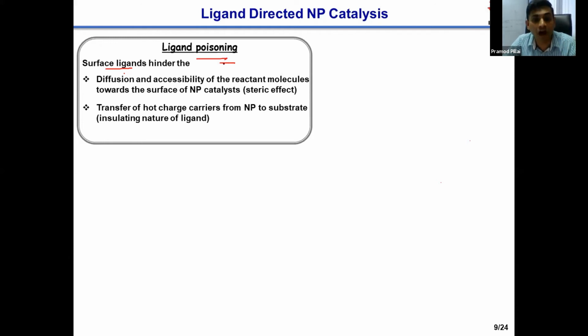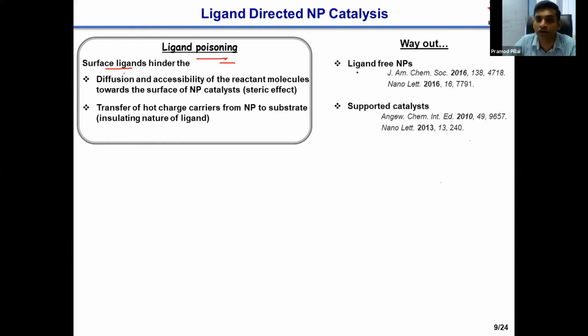So what is the way out here? One of the ways is to work with ligand-free nanoparticles where you don't have any traditional ligand. So these nanoparticles will be stabilized with some small molecules like some hydroxide or some sulfide ions, and they can be used for catalysis. So this is a very good strategy, but the problem is that during the catalysis, the stability of the nanoparticles gets compromised because you don't have a traditional ligand which will stabilize them in a solution state.